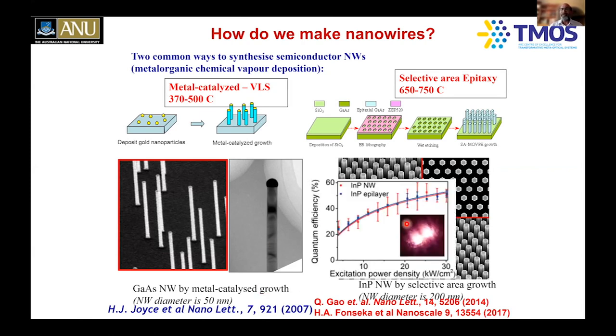We've taken these indium phosphide nanowires and excited them with a laser pulse to generate electron hole pairs, and then looked at how the electron hole pairs recombine and emit light. We quantify the quantum efficiency of the light emission as a function of the laser excitation power. You can see the red curve is for the indium phosphide nanowires, showing a quantum efficiency of about 50%. The blue curve is for the epitaxial layers, which are two-dimensional layers. Both have similar quantum efficiencies, indicating that in the case of nanowires, the surface broken bonds do not play a significantly detrimental role in the case of indium phosphide. That is not always the case. For example, in gallium arsenide, they really create havoc, which I will not have time to go into.